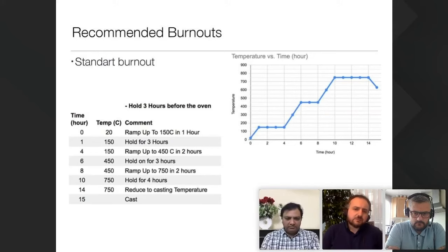So this is a standard burnout that we can recommend. I wrote there, hold 3 hours before the oven, so you leave it outside for 3 hours. You put it in the oven, go to 150 degrees, hold for 3 hours. Actually, what happens inside your flask doesn't reach 150 - it stays around 100 degrees because the water is boiling. So you're at 100, 110 degrees, but you leave it long enough that the water evaporates.